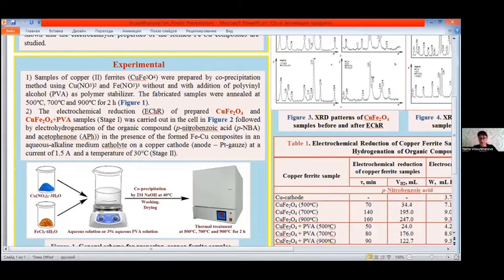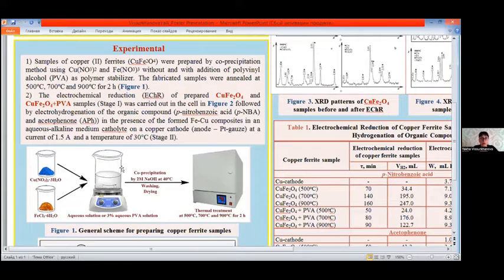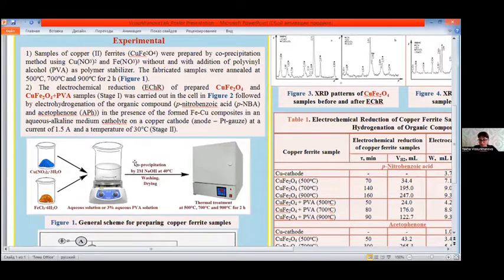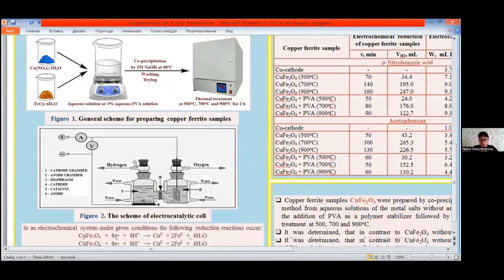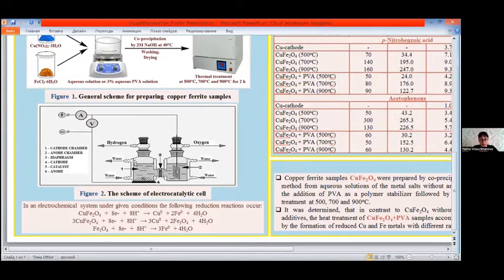The copper ferrite samples were prepared by co-precipitation method using copper and iron salts without and with the addition of polyvinyl alcohol as polymer stabilizer. The fabricated samples were heat treated at 500, 700, and 900 degrees Celsius for 2 hours. Here on this poster, you can see the general scheme for preparation of copper ferrite samples. Next, the heat-treated copper ferrite samples were deposited on the cathode surface in the electrochemical cell with the aim to reduce them. The scheme of the electrochemical cell is shown in figure 2.